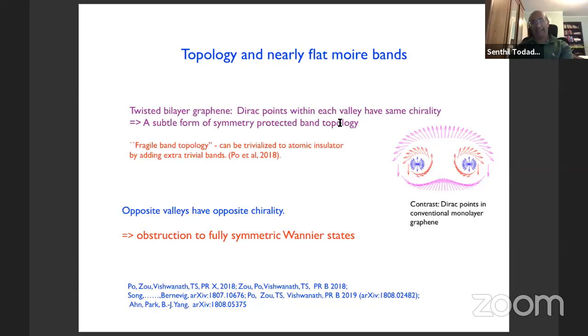So the Dirac points within each valley have the same chirality, meaning the phase of the electron wave function winds around in the same sense as you go around either of the two Dirac points within a single valley. This should be contrasted with Dirac points in conventional monolayer graphene, where there's a plot of the direction of the effective magnetic field on the Dirac spinor. This winds around in opposite senses in standard monolayer graphene for the two Dirac points. In contrast, here the chirality is the same for the two Dirac points. So this feature is connected to a subtle form of symmetry protected band topology known as fragile band topology.